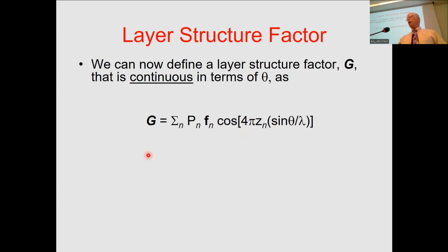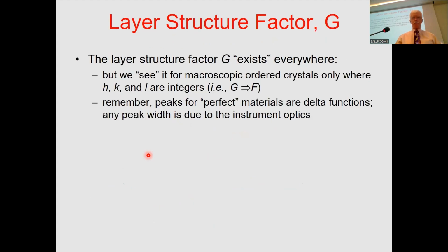Now you might wonder, how do we worry about peaks? The layer structure factor exists everywhere, but we see it only for macroscopic ordered crystals where H, K, and L are integers. And so we only get to see the layer structure factor right at that one peak position. The peaks are delta functions.